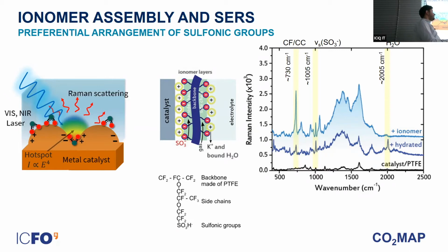So you have the CF and CC groups, and you have the sulfonic acid group here. The interesting thing in this plot is to see how the relative amplitude of these two peaks, the sulfonic acid and the other peak, changes when you hydrate the sample. Once you immerse this in water, which is the operating condition of this electrode, there is a change in the relative amplitude of these two peaks, making the contribution of the sulfonic acid more prominent. And this hinted to us that the functional group closer to the surface of the copper electrode is actually the sulfonic acid group, meaning that the copper catalyst has access to these ions and to water as well.